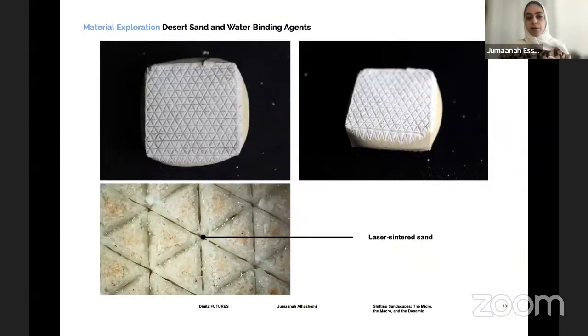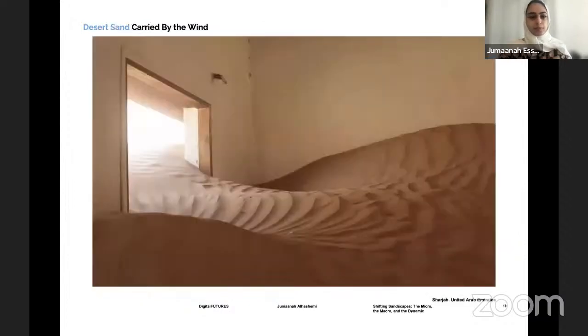And this is using finer grains of silica sand. As you can see, because it's quite fine, it looks extremely neat when it comes to the laser sintering, and the glass penetrates through evenly and nicely. It's about seeing what occurs with the sintering as it creates this molten glass. The more you run it through the sintering process, it will keep forming more glass. But it takes a really long time though. This piece took about 4 hours to sinter to something close to glass.